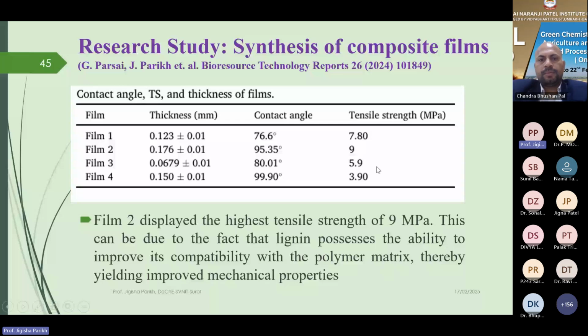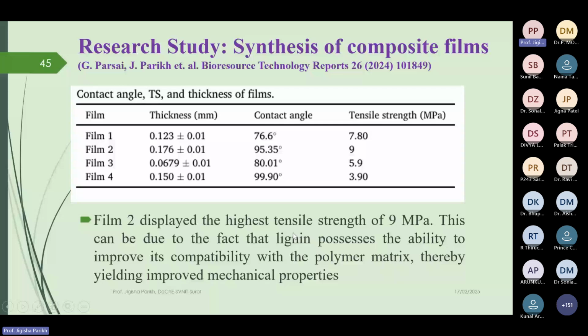It should not crack or fracture or be torn away. So minimum tensile strength is required. So that has also been measured from those films. If we compare these four films together, film 2 displays the highest tensile strength of 9 MPa. So this is because film 2 contains the lignin, which possesses the ability to improve its compatibility with the polymer matrix. Okay, because it is a very typical type of polymer, and thereby improving the mechanical properties. Okay, so here one is the comparison, and another one is the utilization of these different films for different applications. Okay, depending upon the characteristics which we receive out of these films.